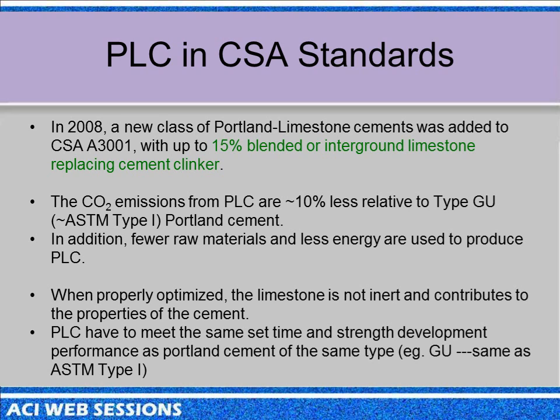So typically these Portland-limestone cements have about 100 points higher Blaine fineness to get the clinker at the same fineness it was before, but you've got this increased fineness of the limestone particles. And you also have a wider distribution of limestone particles, therefore you get a number of benefits in terms of shrinkage and finishing properties. In Canada, the Portland-limestone cements have to meet exactly the same physical properties as Portland cements. So from a concrete producer's perspective, they shouldn't see the difference.